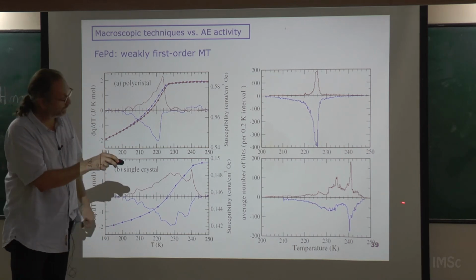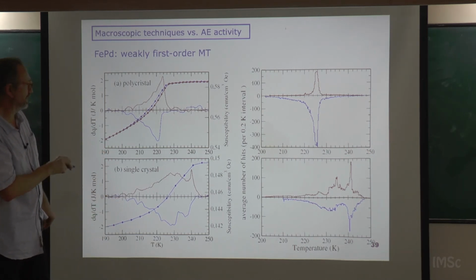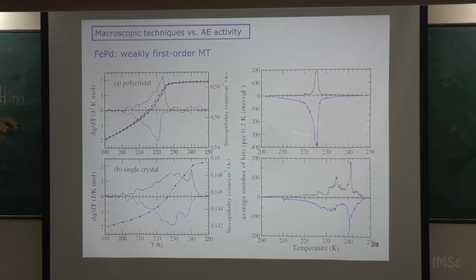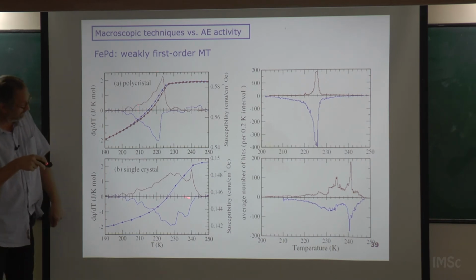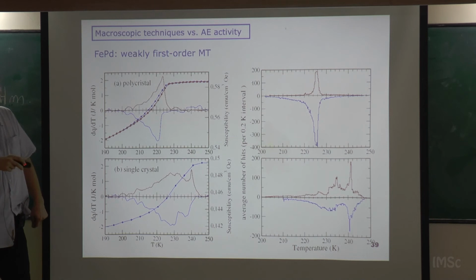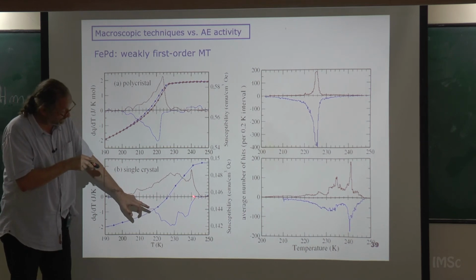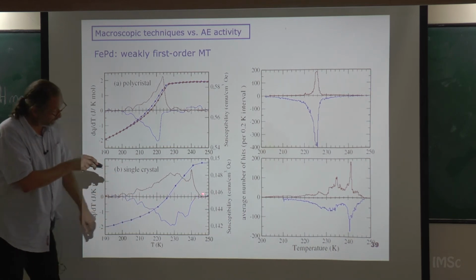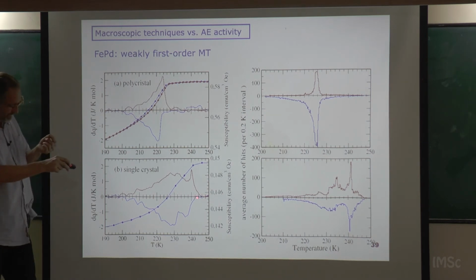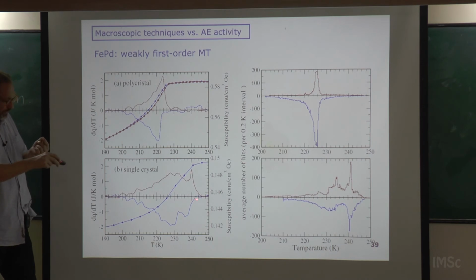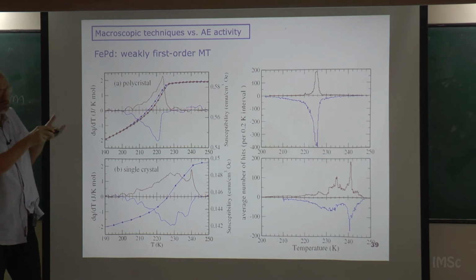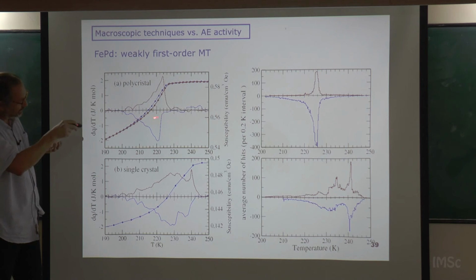And this is for a polycrystal. For a polycrystal, you cool and you heat. Okay, I'm wrong. This is the polycrystal, sorry. This is the polycrystal and this is the single crystal. When people were doing calorimetry in this problem, they were saying that there was a hysteresis in the transition. You see here that this curve seems to be shifted from the red. Let's say, the starting point when cooling is this one, and the finishing point when heating is that one. And here, it depends on how you put the line, but in calorimetry you have to put a line. It also seems that there is a shift.